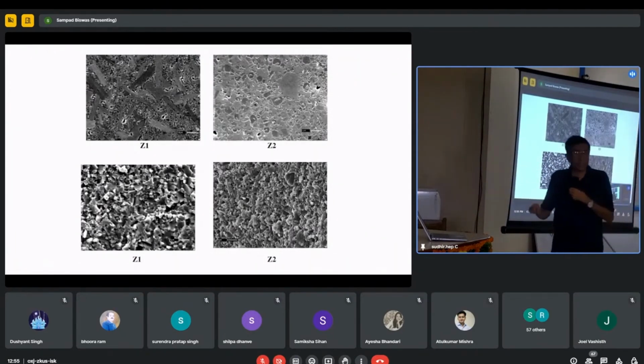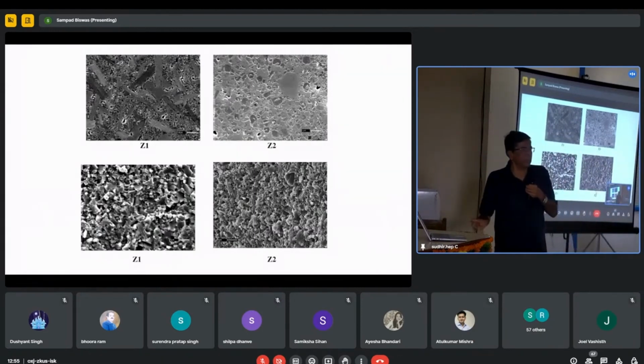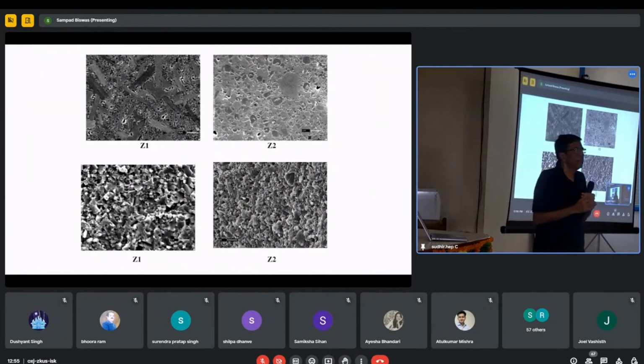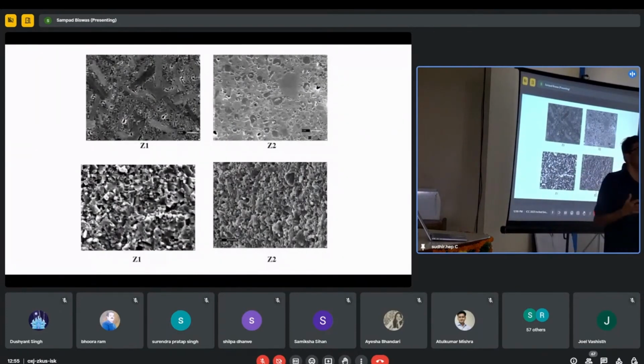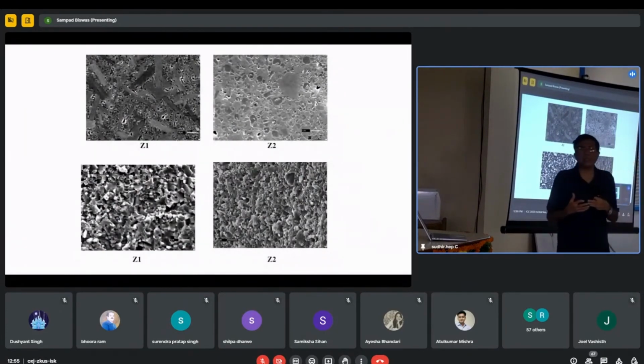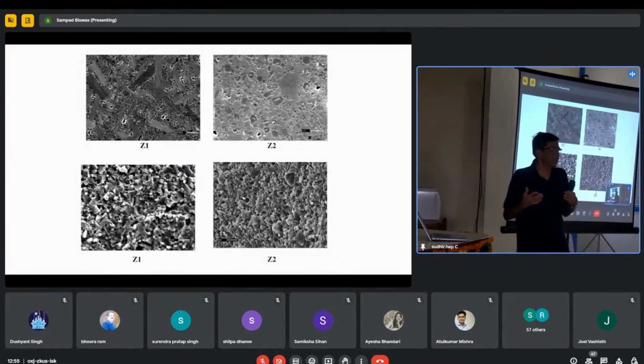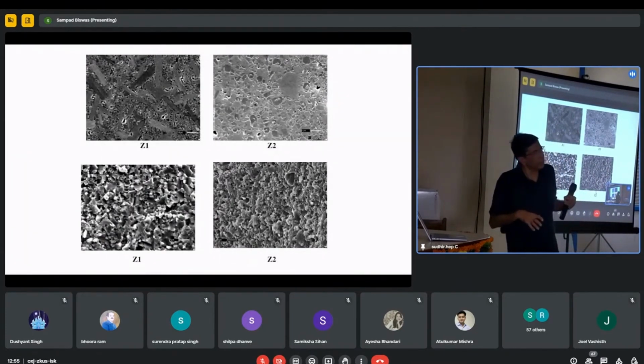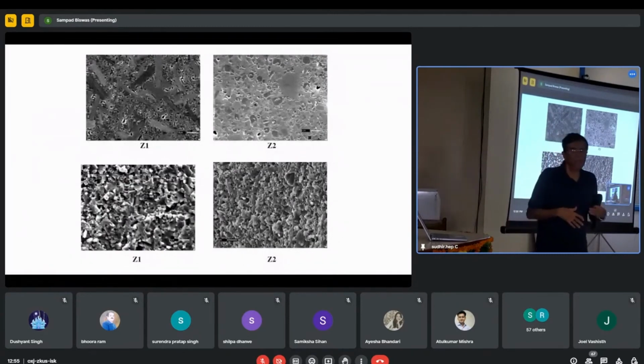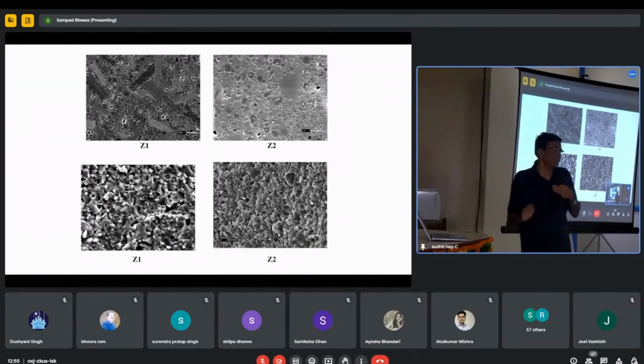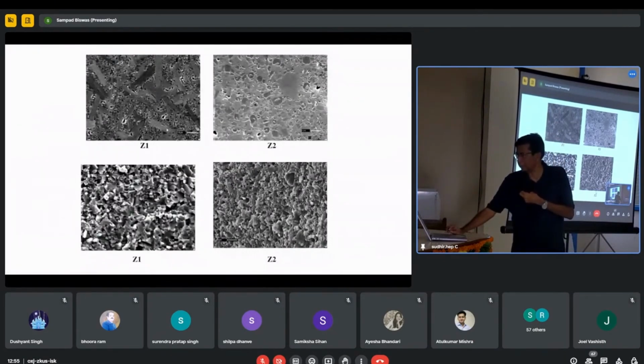So we carried out our experiments with these two silicon carbides, preferably in line with the commercial armored silicon carbide available in the international market. So we developed the material here, and then we carried out our further experiments here. The grain sizes of these are very small. Here you can find heterogeneous grain sizes. One is longer, the other one is very small. Now let us see how it happens.